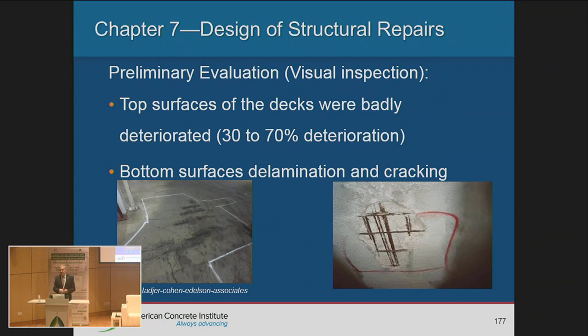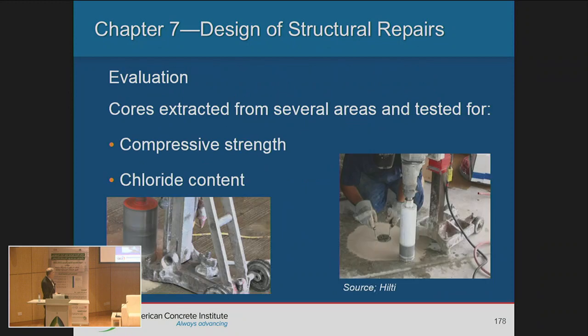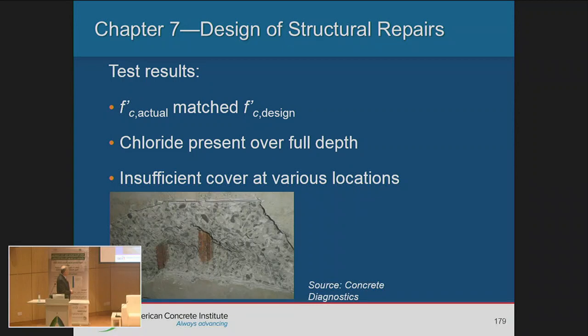As mentioned, Chicago means there is snow. Snow means they spray salt. Salt is carried by the cars into the parking garage. When it goes into the parking garage, there is chloride contamination. That means steel corrodes. So here we're showing some delamination of the underside of the slab, and here the top side of the slab. For testing, they took samples to test the concrete compressive strength and the chloride content within the concrete.